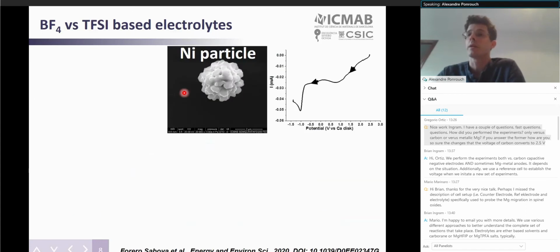So to try to better understand these differences, we went to several characterization methods. Starting from microscopy, we used nickel particles as working electrodes, on top of which we deposited the passivation layer by polarizing these nickel particles towards negative potential value, reducing the electrolytes on top of these particles.